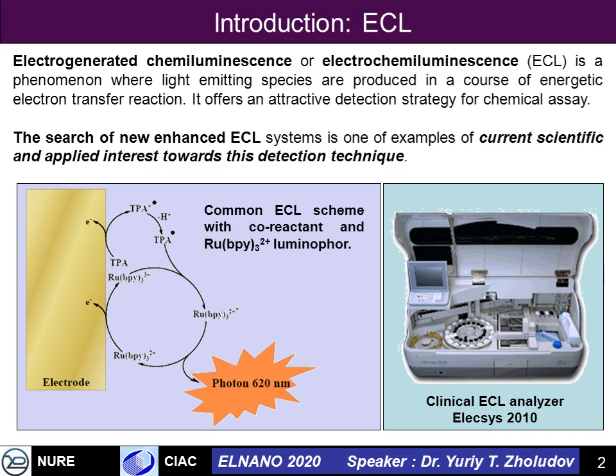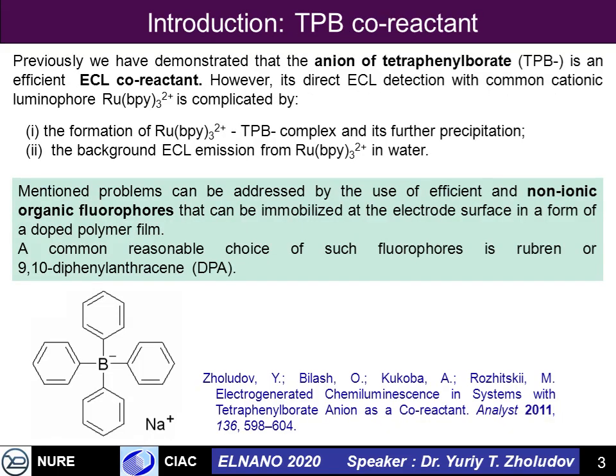Among the basic current directions and trends in ECL research is the search for new detection techniques and new ECL systems. Previously in our research we developed and demonstrated a new ECL coreactant, sodium tetraphenyl borate. It is a quite efficient system, but it has some disadvantages compared to commonly used ones like tripropylamine. For example, it cannot be efficiently used with commonly used fluorophores like the ruthenium trisbipyridyl complex, because it creates a precipitate with it and gives some background emission from the Ru(bpy)3 itself.